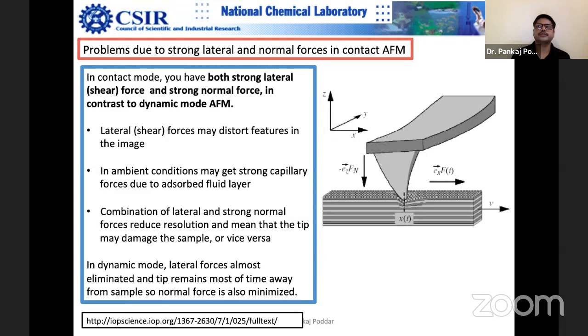Poddar mentioned that contact mode imaging gives high resolution. It gives high resolution only when the tip is intact. The tip quality matters a lot. If the set point is too high, and if you are dragging the tip too much, then you're not going to get high resolution. Forget about that.